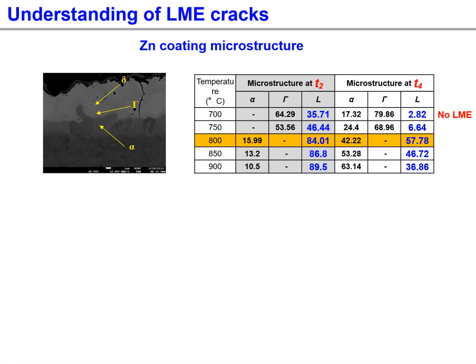We tried to explain the LME sensitivity with the zinc coating microstructure analysis using SEM-BSE mode by analyzing the ex situ phase constituents such as delta, gamma, and alpha. We can predict the in situ phase constituent and phase fraction at each testing temperature. At a testing temperature of 700 degrees Celsius, less than 3% of liquid zinc was available, so there was no LME cracking. However, with the increasing testing temperature, a large increase in liquid zinc fraction was observed, and 58% of the phase was liquid zinc at a testing temperature of 800 degrees Celsius.